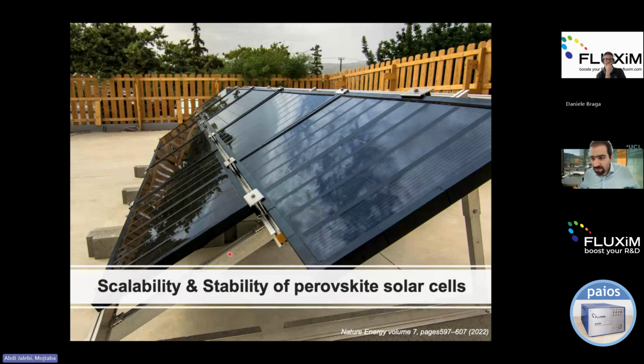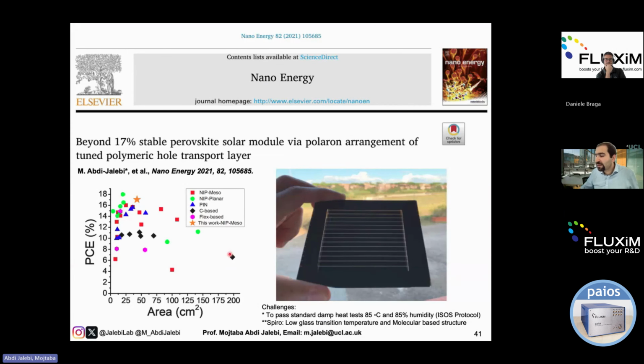All right, so I think I have a few more minutes to talk very briefly about the scalability, and then we can go to the questions. On the further stability and scalability of this perovskite technology, we also work on making perovskite modules. One of the challenges, if you want to pass the stability test, especially at high temperature and high humidity, is replacing the hole transport layer, the common one, which is spiro-OMeTAD, which has a low glass transition temperature. Replacing it with the polymeric HTL helps us pass all the stability tests at 85 degrees and 85% humidity, and at larger scale based on the ISOS protocol.